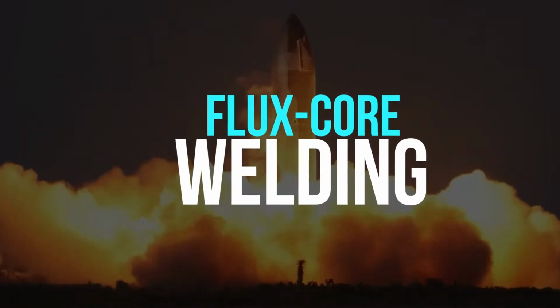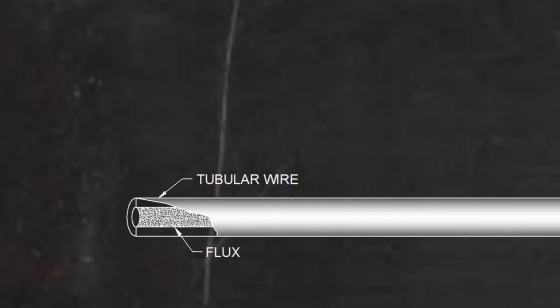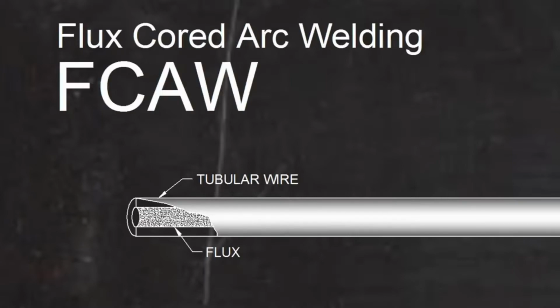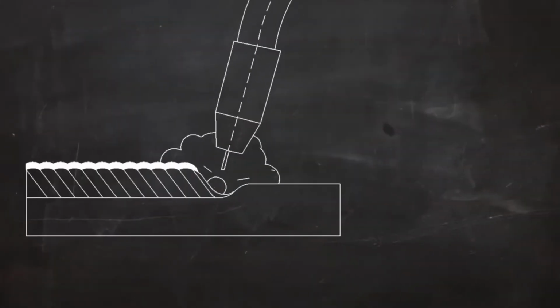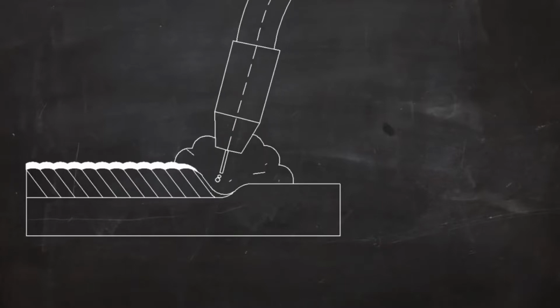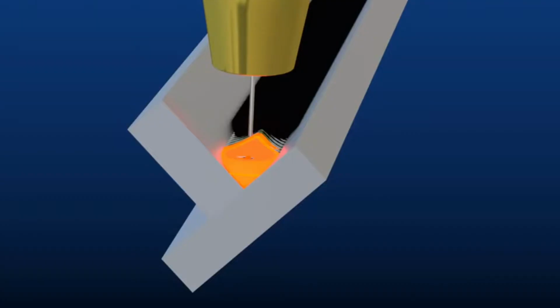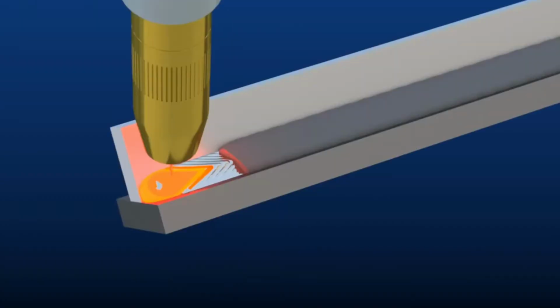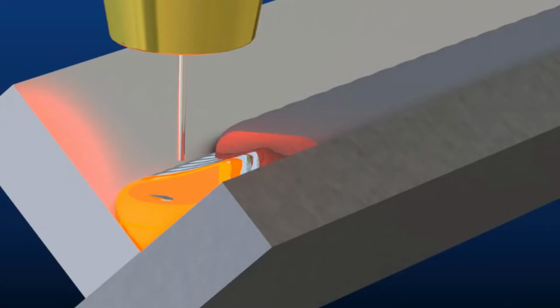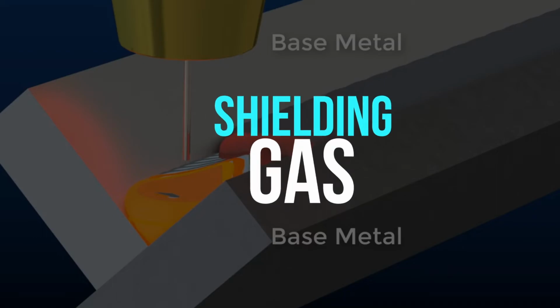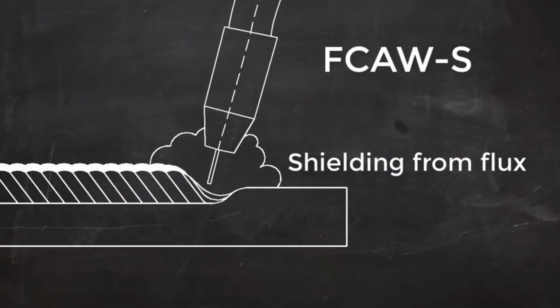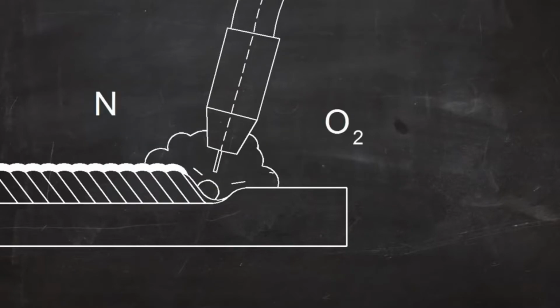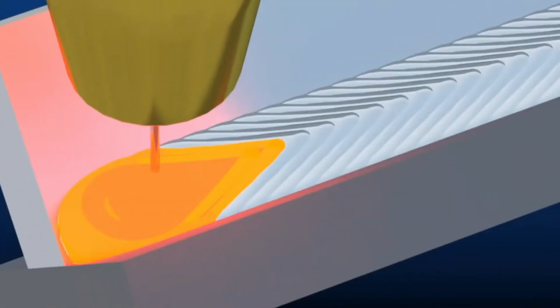The early Starship prototypes were built using a welding method called flux core. In this method, a metal wire is subjected to a voltage that causes an arc to form between the wire and the metal, causing the metal to melt. The metallic wire's tip melts as well, falling into the melted stainless steel to fill up any gaps and cracks that might have been there. Flux core welding involves wrapping the metal wire in a solid substance that, when burned, creates a shielding gas around the weld junction. This protects the weld and keeps it from interacting with nearby oxygen, which might potentially lead to failure. Each ring is made of a single significantly thinner sheet of stainless steel.